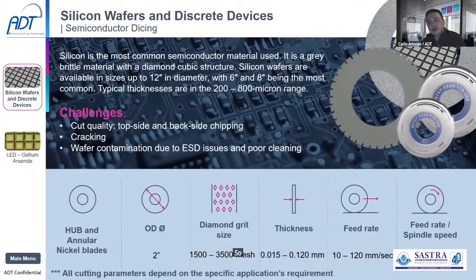So grit sizes, with the combination of other factors, when you create chip size and you're doing it on a very narrow scribe line, is very problematic. So these are a few of the challenges for the silicon wafer that we face currently in the industry. We are almost most of the time doing this with the hub blade. But for customers who are not maintaining a very tight scribe line, and their wafers are silicon wafers with applications on the high side of the thickness, this can also be done with a hubless annular blade.